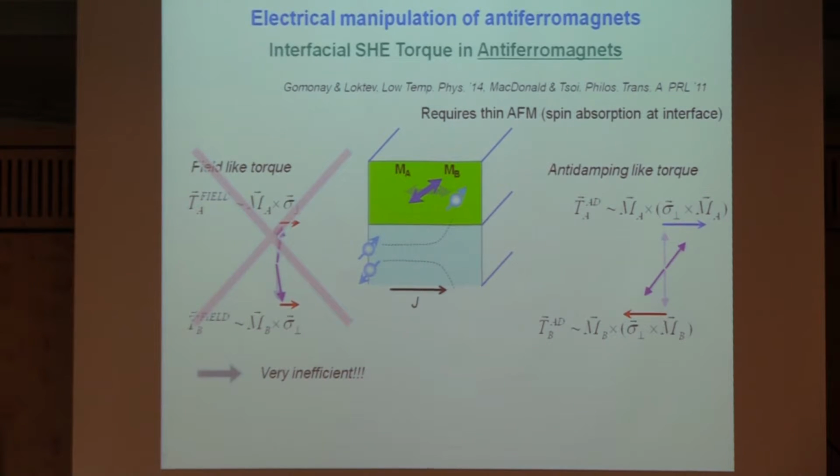So it would be, in case of an antiferromagnet, schematically actually be staggered, this effective anti-damping field. It would be for one sublattice, say in this direction, and for the other sublattice in the opposite direction. So it has this staggered symmetry. We know the field-like term